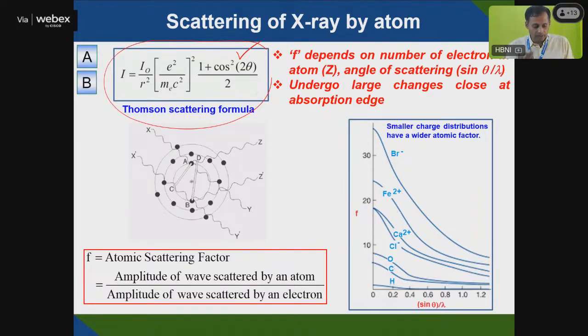But if you see the atomic scattering factor f, it is equal to the amplitude of the wave scattered by an atom divided by the amplitude of the wave scattered by an electron. So you are dividing the whole atom's scattering with respect to an electron. Here, the scattering factor of an atom depends on sine theta by lambda. If you see how the scattering factor changes for bromine, iodine, iron, chlorine, carbon, in all cases your scattering factor is decreasing.